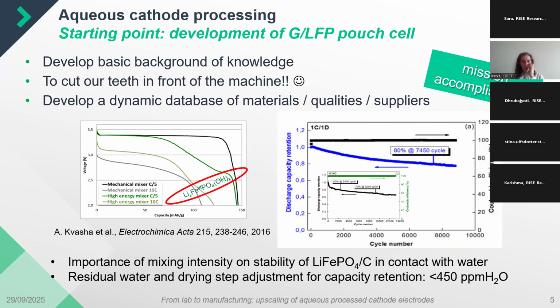We published in 2016 these results with LFP cathode active material, which is a phosphate, not an oxide, so it's more stable and less sensitive to water. It's also carbon coated, which helps with this stability towards water. So it was kind of the starting point and less challenging in terms of all these issues I mentioned that are mostly related to the layered oxides in terms of the cathode.